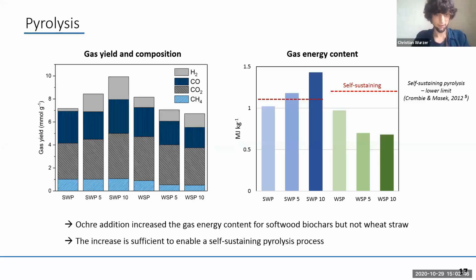And an opposing trend is seen for wheat straw, which still has an increased hydrogen yield, but the total gas yield decreased significantly, about 20%. And here you can see that the feedstock high in cellulose and lignin produces a sufficient amount of hydrogen to actually influence the gas energy content, which you can see on the right. So that's the lower heating value of the gas.